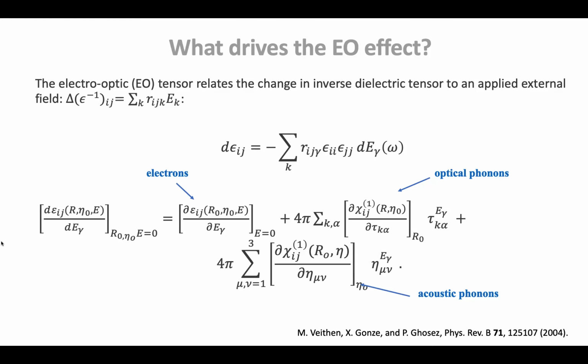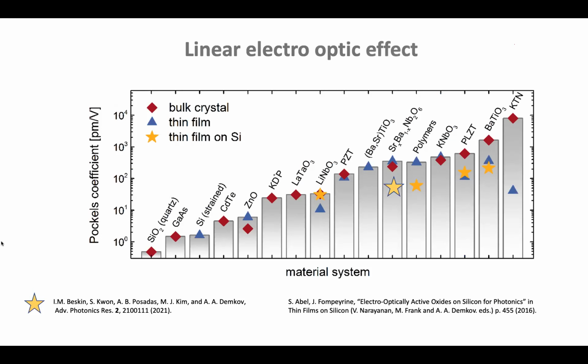If you look at all the materials under the sun which have been measured for electro-optical activity with a linear electro-optical effect, the material everybody is using is lithium niobate, but it actually has a very modest electro-optical response, only 35 picometers per volt. Now, one thing I have to tell you, these are all very weak effects. You measure in picometers, so it's really tiny.